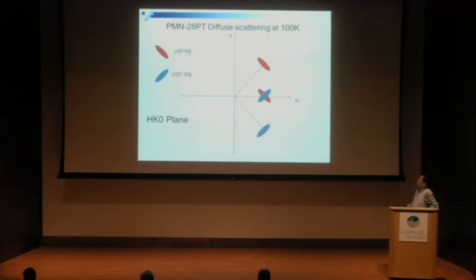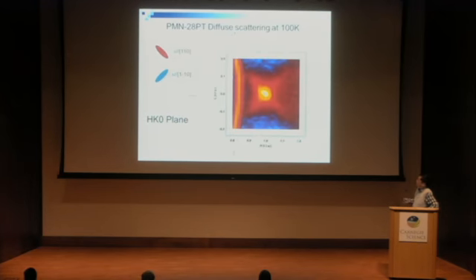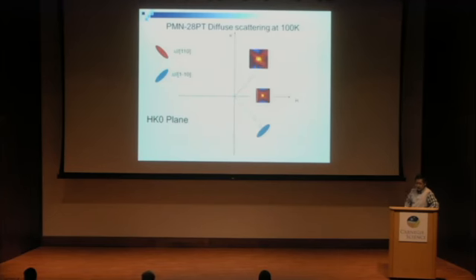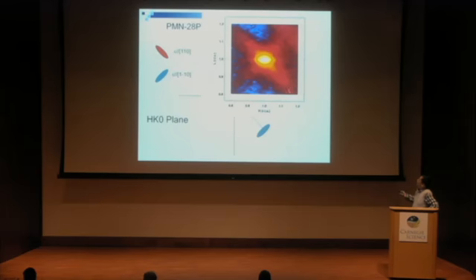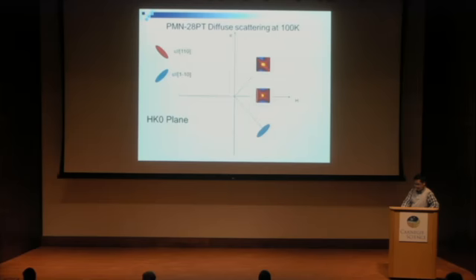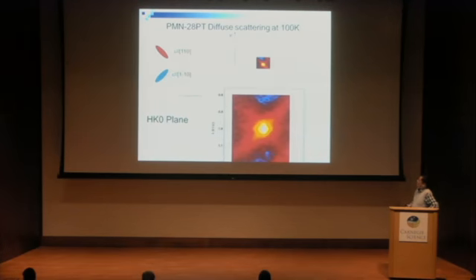Here are some of our recent results in the PMN-28PT single crystal, measured at 100 K in the HK0 plane. Around the 100 Bragg peak, we can see clearly a butterfly-shaped diffuse scattering with both red and blue wings. And near the 110 Bragg peak, it is mainly from the red wing, but there is still some intensity from the blue wing, but much weaker. And near the 1-10 Bragg peak, it's similar, but the opposite way.